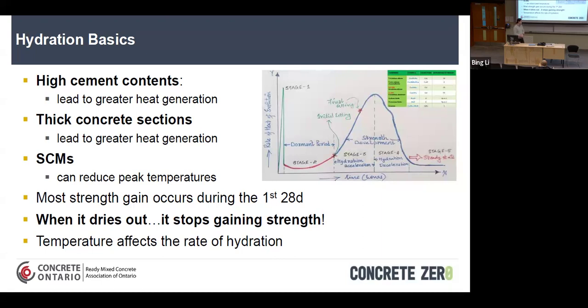Because there's a thing called thermal cracking. You can have the concrete in the center heat up too fast, and the outsides are cool, and it will crack the concrete. It's a differential in temperature, and they will crack the concrete. So that's why we want to control heat of hydration. And you can see here that too much cement can cause a greater amount of heat of hydration. Makes sense because that's the thing that's reacting, that's creating heat for you.